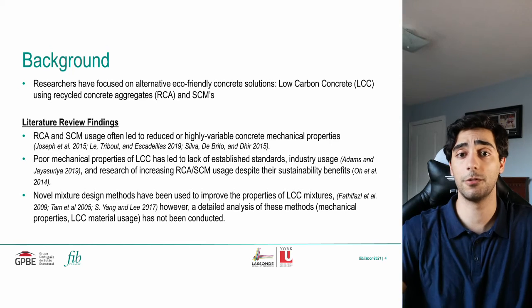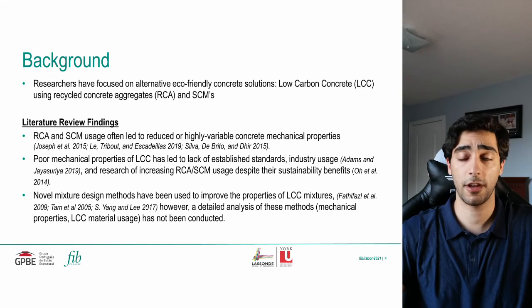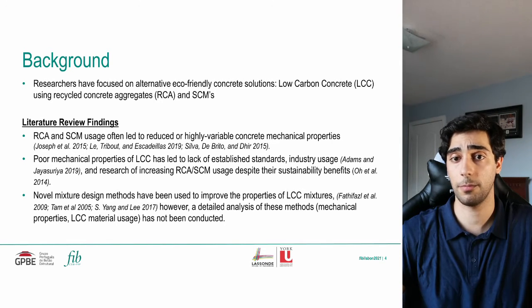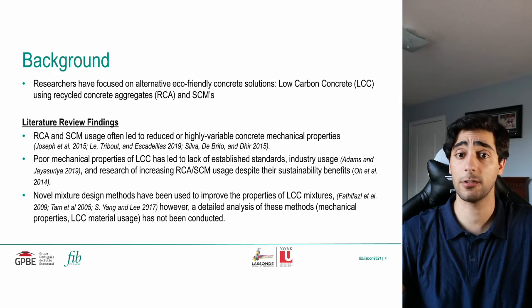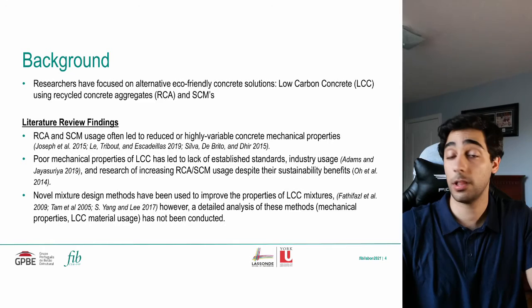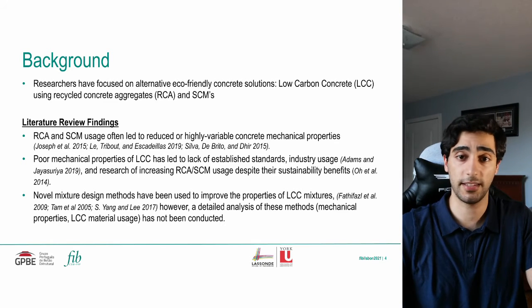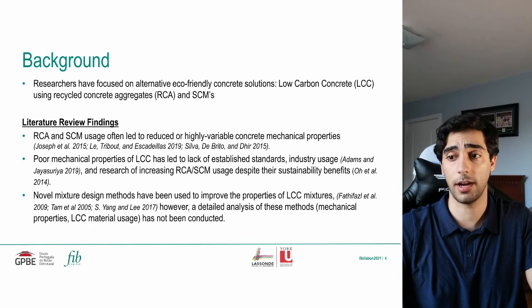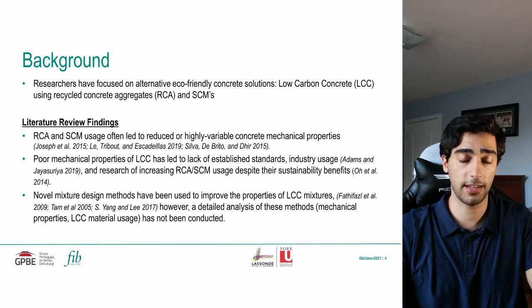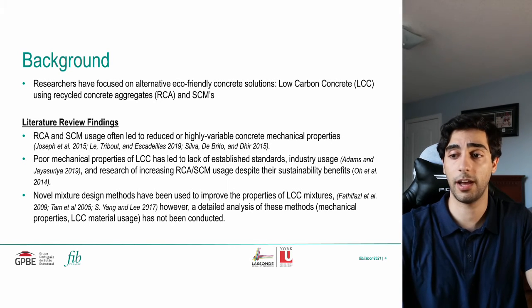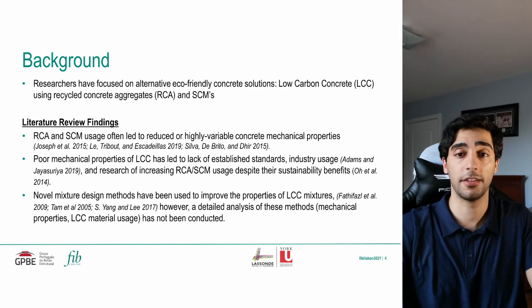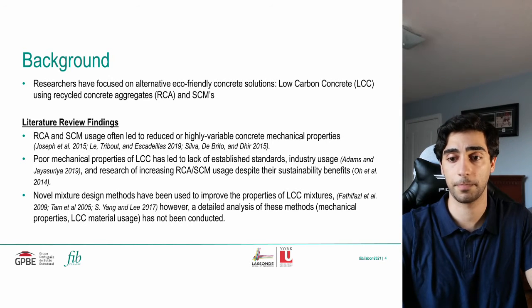Now, in an effort to find a solution for all of this, many researchers have focused on the use of low-carbon concrete produced with recycled concrete aggregates, or RCA, and supplementary cementitious materials, or SCMs. Preliminary studies have found that RCA and SCM usage often leads to reduced or highly variable mechanical properties, and this poor mechanical performance has often led to a lack of established design standards in industrial usage, and further research incorporating higher volumes of RCA and SCMs despite their sustainability benefits.